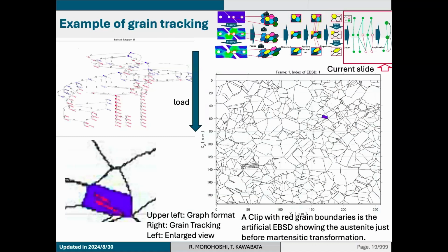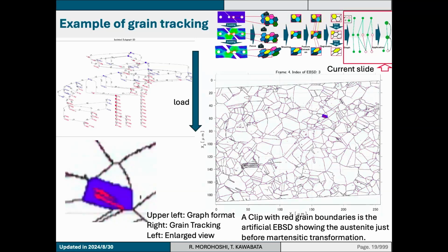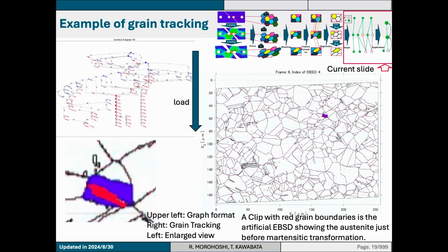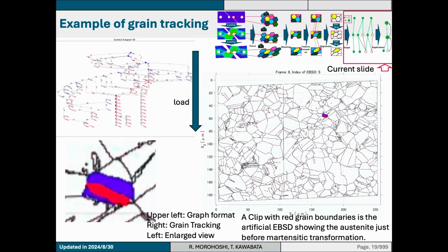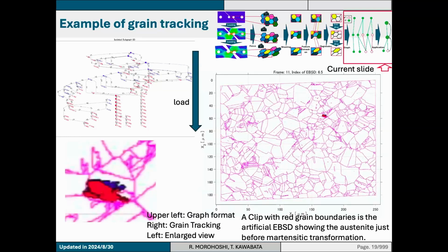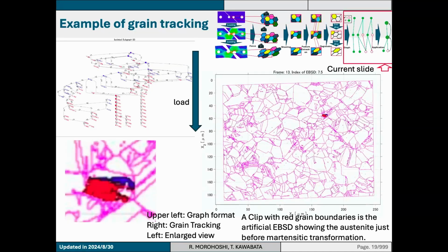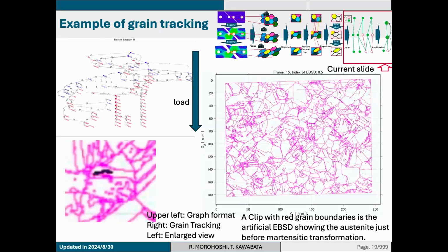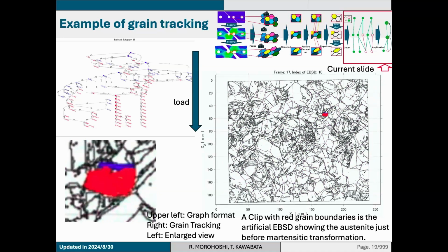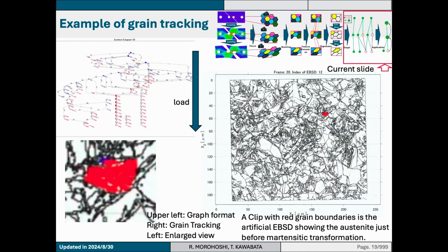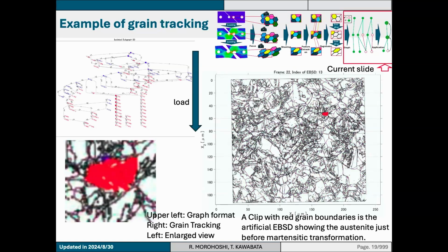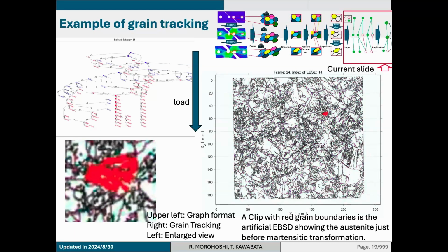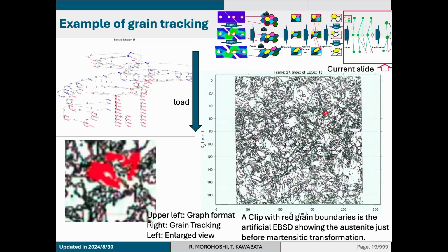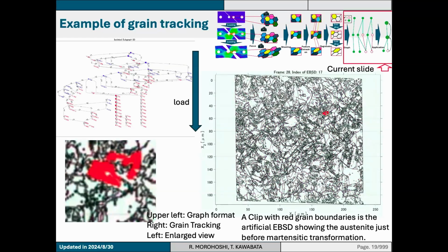And this is the typical example of how the grain tracking goes. These are the subgraphs of the grains, as shown on the right. So we could identify the transition of every grain and when it is transformed into the martensite. And the clip with red grain boundaries is a kind of artificial EBSD showing where the austenite is just before the martensitic transformation.